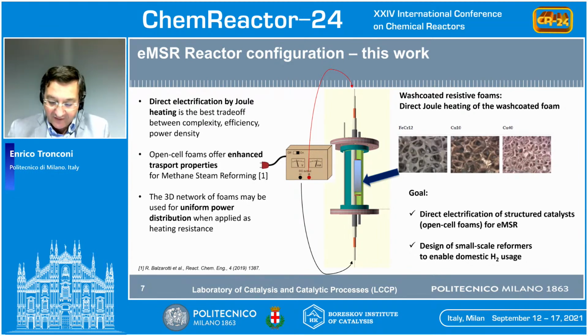And in previous work, we have assessed by combining experimental and computational approaches the superior mass transfer properties of such substrates in comparison to laminar flow in straight monolith channels. So once we catalytically activate the foams by wash coating, for example, the superior mass transfer properties would enable the direct utilization of these materials after direct Joule heating is applied to their continuous thermally and electrically connected structure to provide a significant intensification of the reformer performances, enabling, for example, the design of compact units for distributed hydrogen applications.